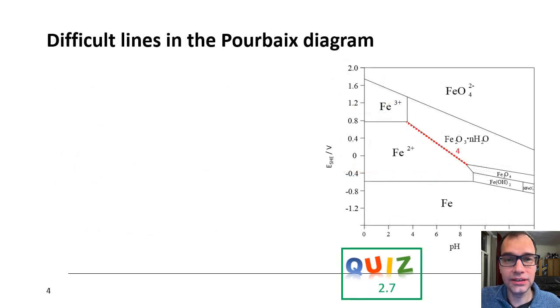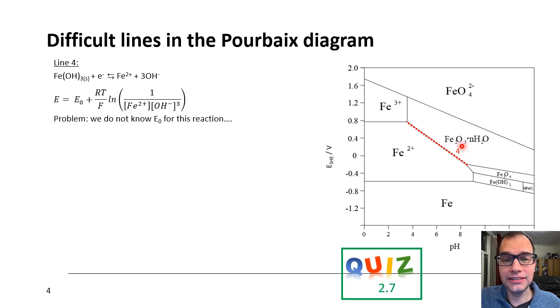Now let's have a look at one of the more difficult lines in a Pourbaix diagram, namely this line 4. It's not horizontal, it's not vertical. And that makes sense when you start looking at the equation. This is the equation that belongs to this line. Iron hydroxide plus electron gives iron 2 plus 3 OH minus. And as you can see in this equation, we have an electron, but we also have 3 OH minuses.